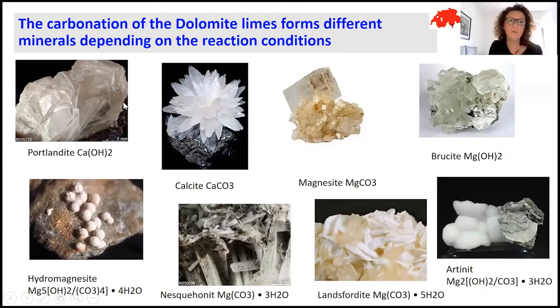And here, for example, we will have portlandite, calcite, magnesite, and brucite, but also different hydrated magnesium carbonates. This depends very much on the reaction conditions: the temperature at which the dolomite was fired, but also the humidity, the temperature in which the setting takes place, the technological process, and so on.